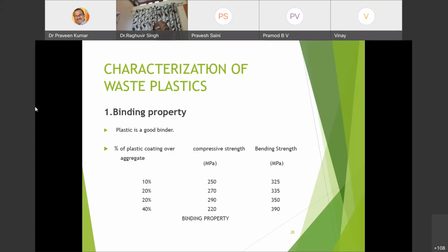With 10% plastic coating, the compressive strength achieved was 250 and the bending strength 325 megapascal. When the quantity was increased to 20%, the compressive strength was found to be 270 and the bending strength 335. At 30% plastic coating, the compressive strength again increased up to 290, and the bending strength increased to 350. At 40% plastic coating, the compressive strength of the aggregate reduces to 220, while the bending strength of the mix increases up to 390.